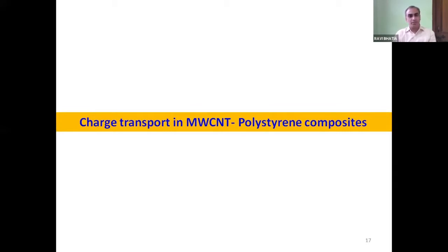There are very important problems which should be tackled before one says that I have prepared a better sample. First is to have the homogeneous distribution of carbon nanotube within the polymer. Second, whether without using any surfactant, one can achieve this homogeneous dispersion or not, because it is well known that carbon nanotube gets agglomerated if left unsonicated, and this agglomeration causes adverse effects on the charge transport properties of carbon nanotube based composite.